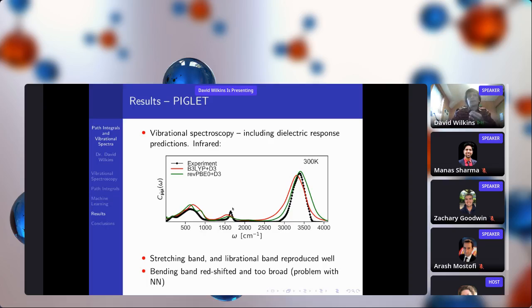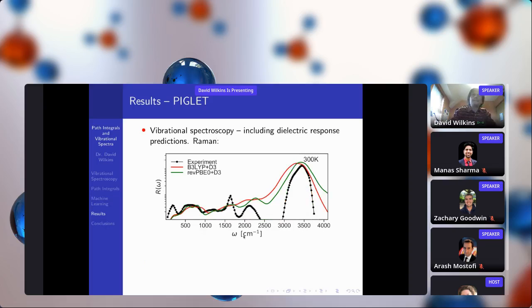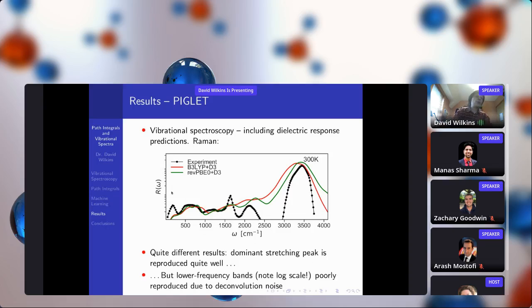And then if we go on to Raman spectra, we see something completely different. The stretching mode is reasonably well described by Piglet. But for the low frequency modes, we do quite terribly, to put it nicely. And the reason for this comes if you look at the y-axis. This is actually a logarithmic scale. And the deconvolution algorithm that we used manages to do pretty well for the high frequency and high intensity band, but it produces noise that really washes out the spectrum at low frequencies. So the deconvolution is the problem.